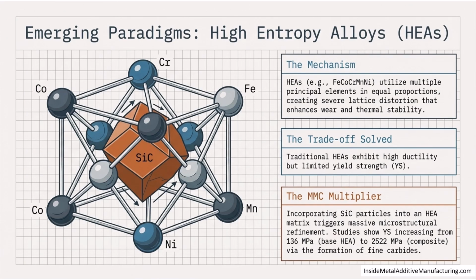One of the most exciting emerging paradigms is the use of high-entropy alloys as matrices. HEAs solve the traditional trade-off of limited yield strength through severe lattice distortion. When we incorporate silicon carbide particles into an HEA matrix like iron, cobalt, chromium, manganese, nickel, we trigger a massive microstructural refinement. In fact, studies show the yield strength can jump from a base of 136 megapascals to a staggering 2,522 megapascals in the composite version.